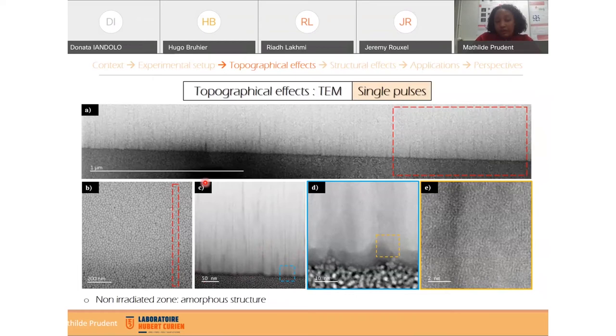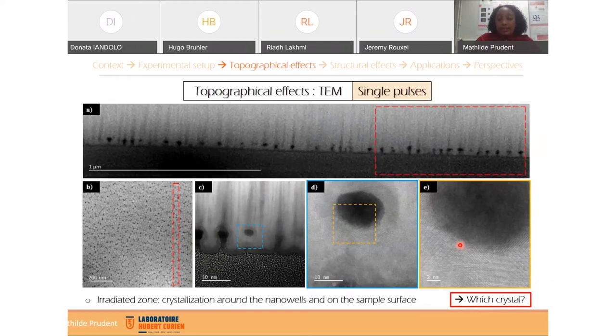In comparison to this analysis, we also extracted some FIB lamella in an irradiated zone after 50 pulses of irradiation. And we can see that here we have the nanowells regularly disseminated in all of the FIB lamella, in all of the sample. And we can see that we have some closed nanowells and also some open nanowells. Around this nanowell, it seems to be some crystallization, and also in the surface of the sample. And to know much more about the repartition of the elements, we realized some EDX mapping after.